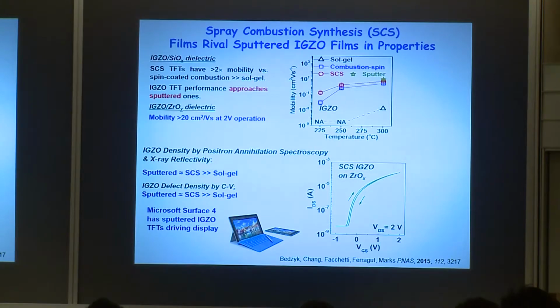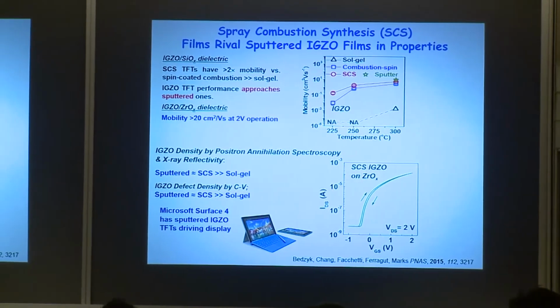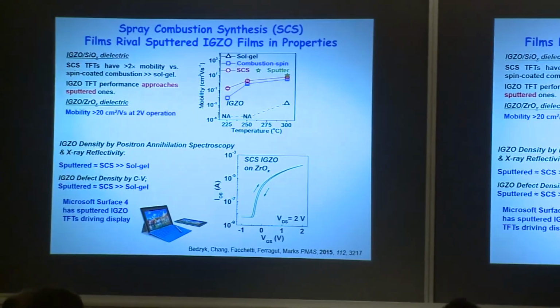I don't think you want to look at all this data, but for the density we used positron annihilation spectroscopy and X-ray reflectivity. Here are current-voltage scans, which look quite good. Here's mobility for films made by sol-gel, combustion spin coating, spray combustion, and sputtering. And you can see the red one, the spray combustion, is almost where the sputtering is.